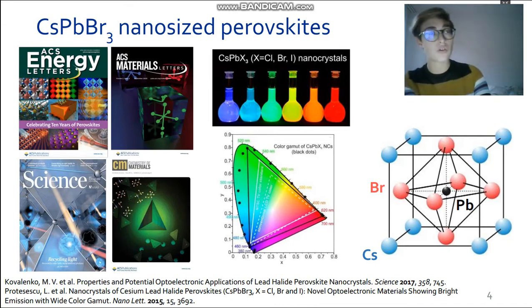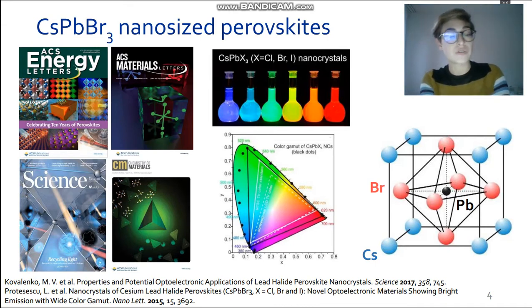The determination of structural properties of nano-sized materials through conventional XRD methods is a difficult task. Advanced X-ray total scattering techniques, and in particular the approach based on the Debye scattering equation computation, are emerging as a successful tool for providing accurate insights on the nanostructure of complex, randomly oriented samples.